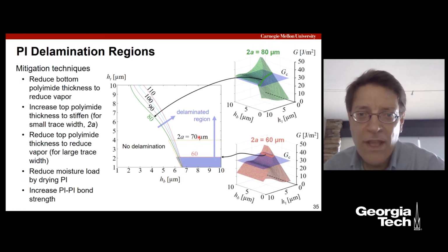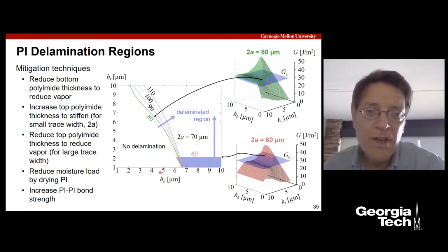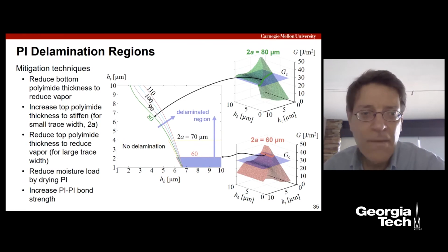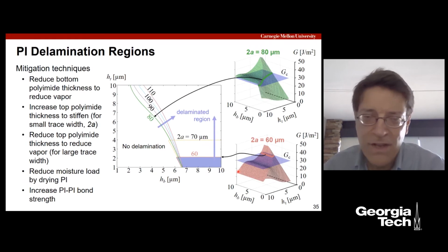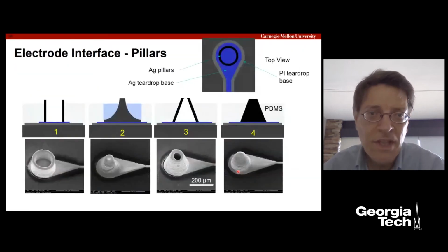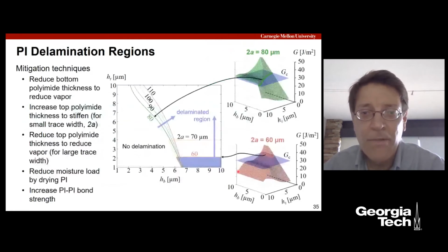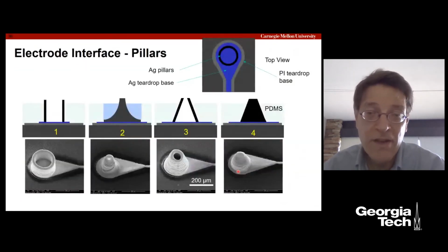But then if we make that wider, what we find is that the delamination region widens out to this whole right side, and now we still want to get no delamination. We basically want a small polyimide thickness on the bottom and on the top. But you can see it's kind of complex. You get different design choices for this. So we solved that problem. So we understand what's going on.